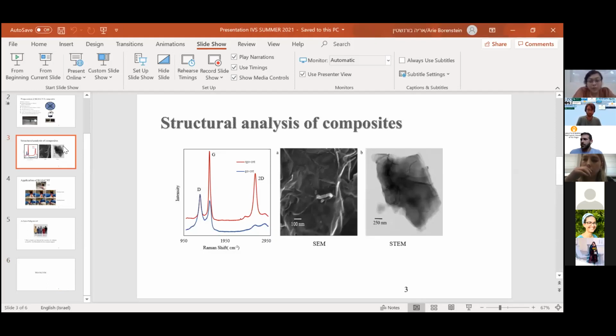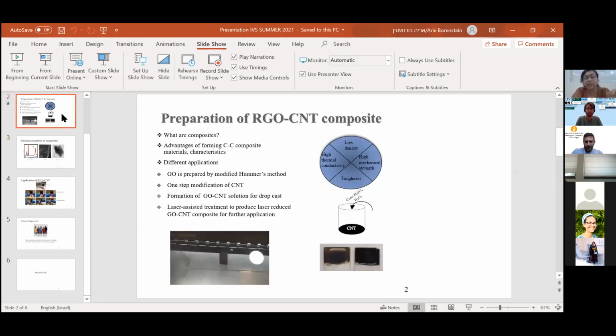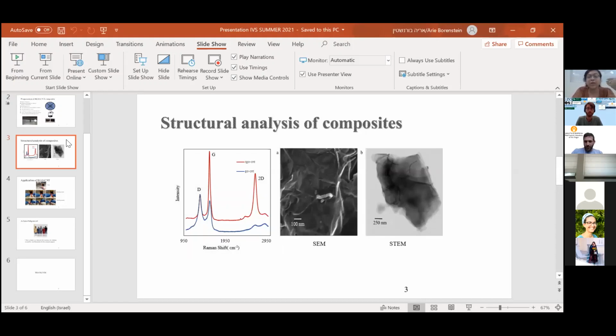So the blue curve is the GO for the composite, where you can see the D band is larger and the G band is shorter. But after the laser treatment that I showed in this slide, the laser changes the material. After the laser treatment, it produces more of a graphene structure. It becomes graphene that we denote as the RGO-CNT. RGO means reduced graphene oxide.